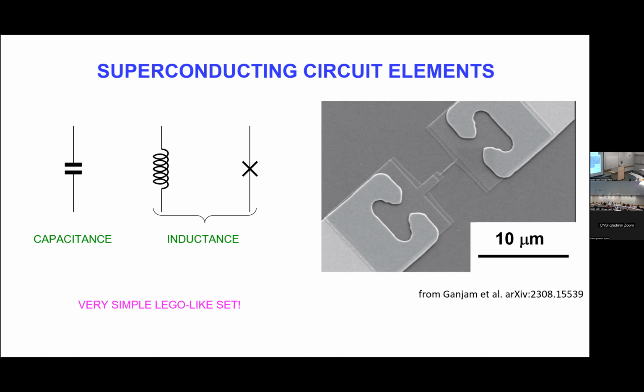It has this native oxide. If you deposit a layer of aluminum and you just introduce a little bit of oxygen in this chamber, this native oxide will grow. It will grow with the exact thickness that you want, and it is a very, very good oxide. You can get a conformal coverage of your metal. So that's the second miracle, an oxide which is at least as good as silicon oxide, which is crucial for